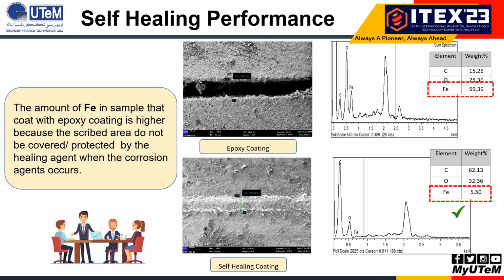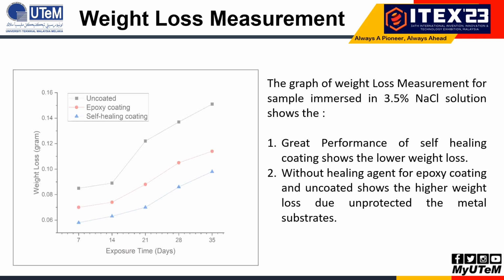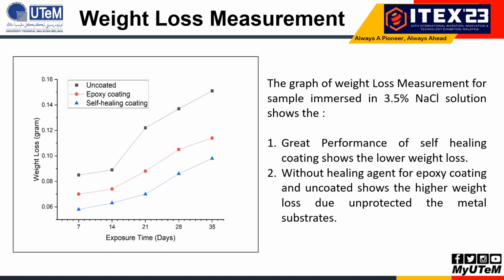For the weight loss measurement, we can see the graph that shows three types of coating: the black one is uncoated, the red is coating with epoxy, and the blue one is the self-healing coating. The graph of weight loss in 3.5 weight percent sodium chloride solution shows that the self-healing coating shows great performance, with the lowest weight loss. Without the healing agent, the epoxy coating and uncoated show higher weight loss due to the unprotected metal substrate.